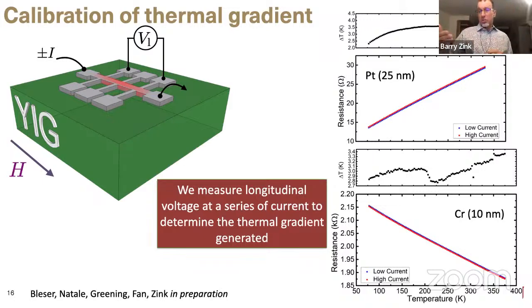So we measure the resistance of the platinum or the chromium, whichever metal we're using. And we measure it in two different cases: a very low current that doesn't cause any heating, and then a somewhat higher current that causes some heating. We calibrate that resistance to use it basically as a thermometer, and then we always know what at least the average temperature of the metal structure is at any time in the experiment. So that's how we're defining the thermal gradient in all the rest of the data that I will show.